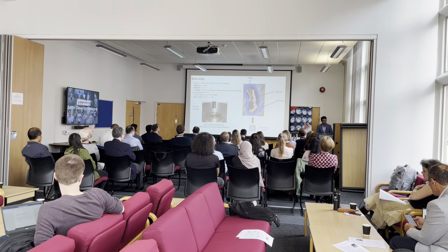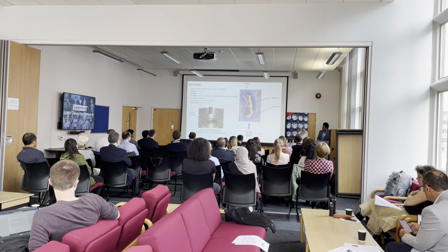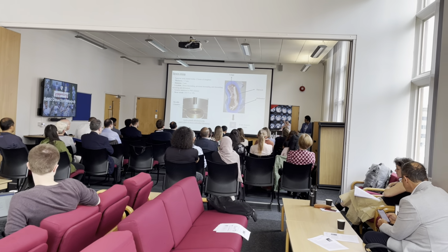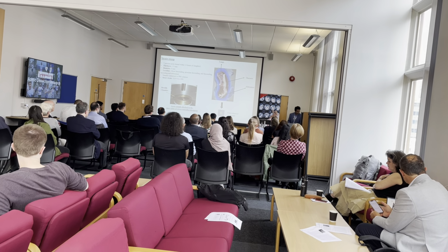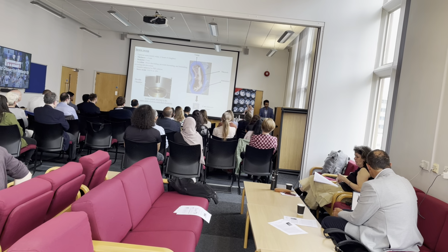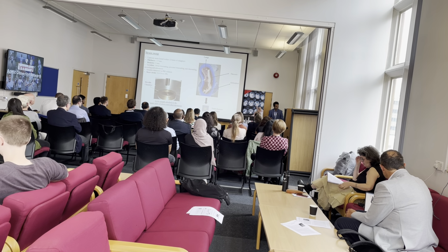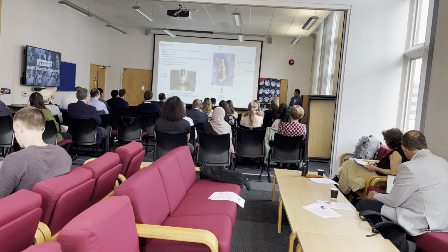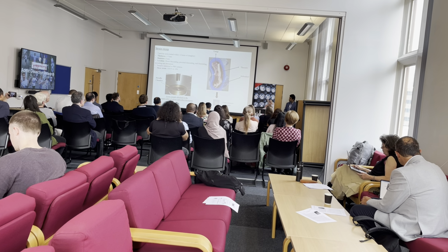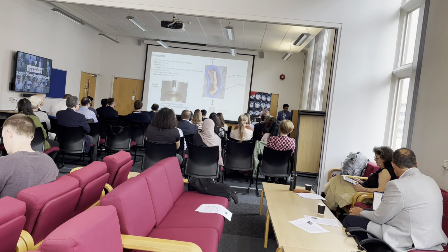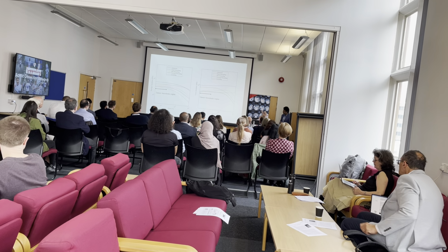So we had 1.5 mm thick aortic samples. I was able to cut them into very nice 8 mm diameter samples, which you can see there. And the locations vary from distal descending region, proximal descending, mid descending, ascending, and the abdominal region. And all these samples were immersed in PBS solution, because we also needed to make sure that we are able to hydrate these particular samples across the testing. So this was one of the key takeaways.